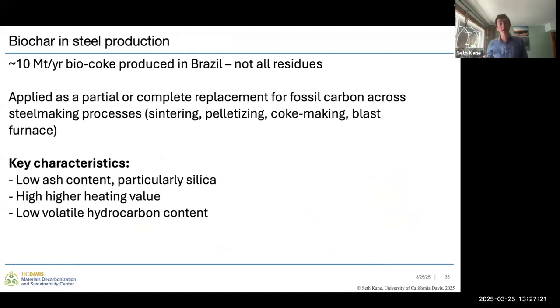Okay, so in steel production, as mentioned, we do use about 10 million tons a year of bio-based coke, mostly in Brazil, but that's not all from residues. This can get used across the steel production process. So we have different carbon inputs of either coal or coke in the sintering and pelletizing process. We have coal inputs to the coke making process that can potentially be replaced with biomass-based carbon. And then we have coke inputs to the blast furnace.